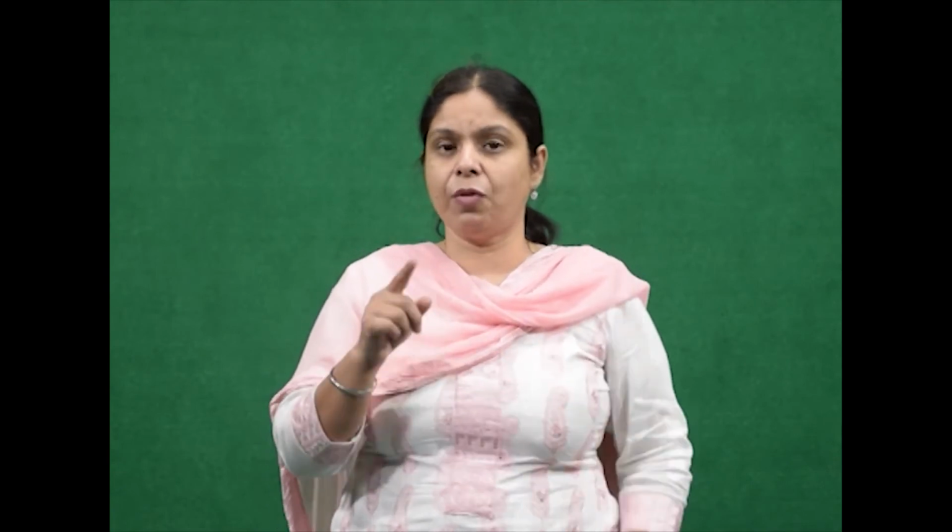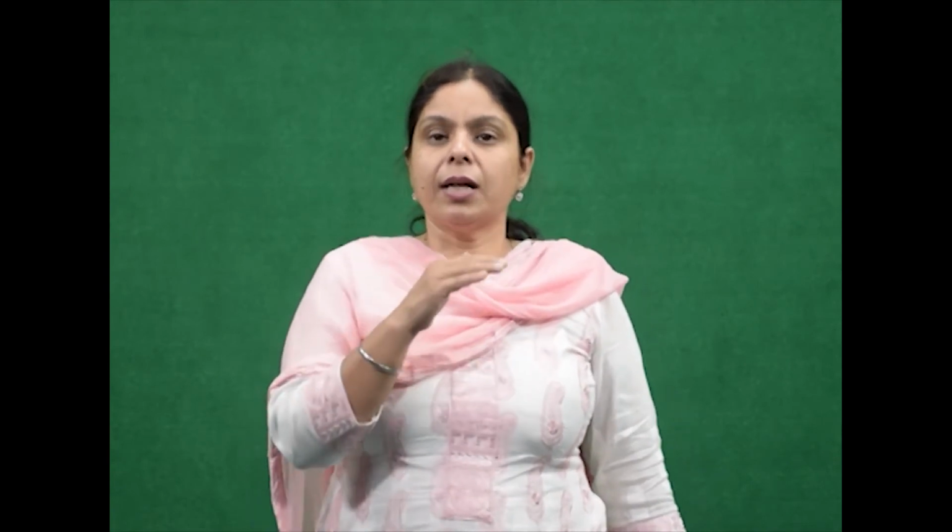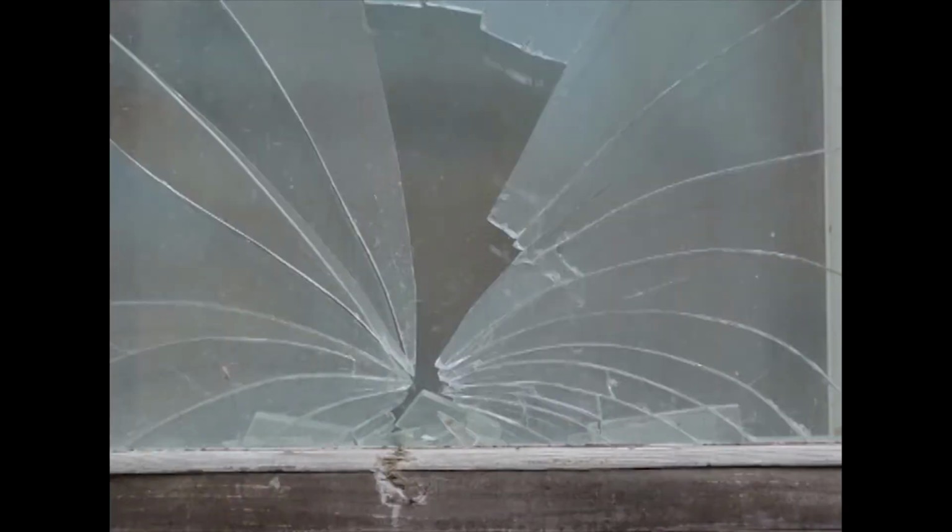Each piece of glass is briefly sketched and marked for reference. A clean and dry sample of crime glass particle, which is again an important precaution, is placed in a small beaker containing bromoform. The glass will float on the liquid surface, indicating that the density of the liquid is greater than that of the glass.